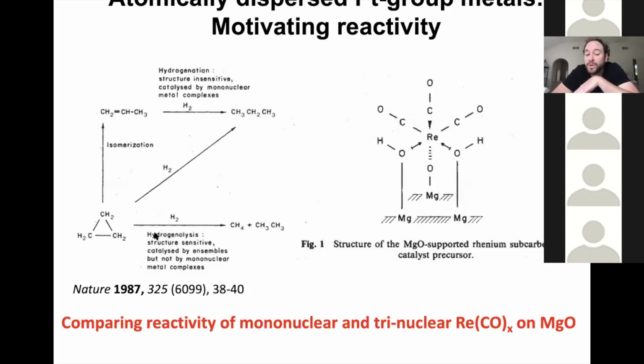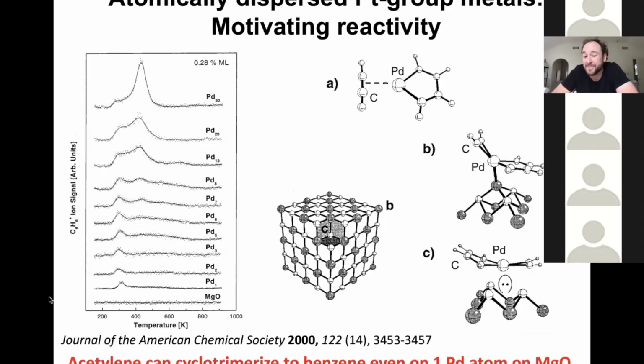However, only when you have those 3 atoms together in an active site, so a trinuclear rhenium species, do you get this hydrogenolysis reaction where you start breaking carbon-carbon bonds, producing methane, producing ethane. So this was demonstrating structure sensitivity down to the limit of 1 atom versus 3 atoms in the active site, showing that there may be some interesting behavior if you can do catalysis by species that are just 1 atom active sites. You can take this further in another paper.